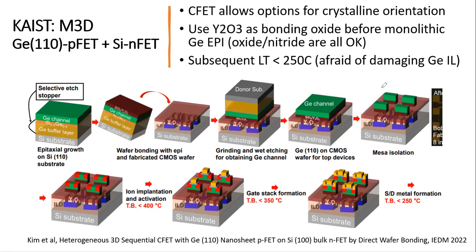It's really not a good idea to have 250, because in a real world device, you have to put the copper back-end-of-line on top of germanium. Those copper back-end-of-line processes have to be about 400 to 500, right? They will not go above 500, but definitely go above 400. So imagine you put a lot of copper lines, many layers on top of this one, then the device will be killed. So these are all useless stuff. Unfortunately, it's good for a demo, but in the real world, probably not going to work.